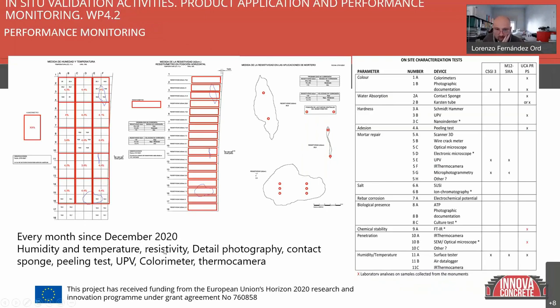So every month since December 2020, we have had an agreement with the University of Oviedo in order to take measurements of this test, and we measure humidity, which you can see on the left. This is a grid, and you can see there is a pattern of humidity here. Also, we took values of temperature to see over time whether it has any relation. We took resistivity before and after, and inside the mortars. And also we took detailed photography in order to see if the contact of the mortar was good